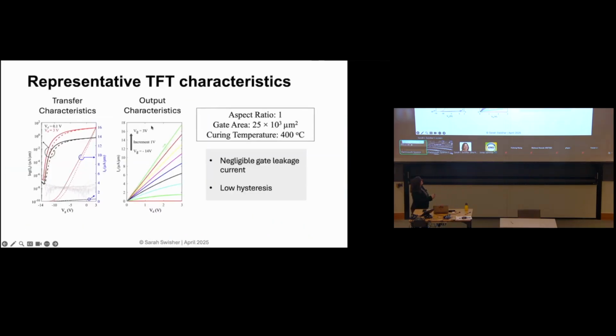And what we can observe is that if we look at our transfer characteristics, we have a little bit of hysteresis, but not much. These devices are turning on at a negative voltage, which is very common for these oxide semiconductors. This device is an example: a square gate with an aspect ratio of 1 and 25,000 square micron area. The temperature that this gate reached was about 400 degrees C. So very little gate leakage and pretty low hysteresis.